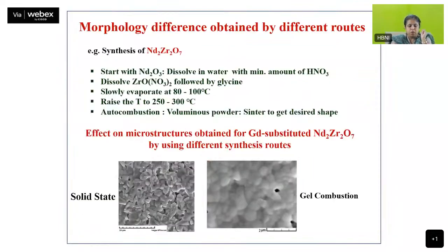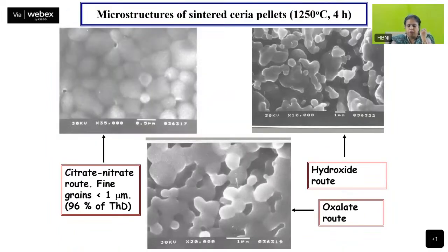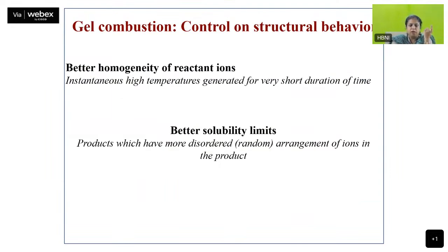Now, just a comparison. This is the Nd2Zr2O7 synthesized by solid state, and this is by gel combustion. You get nice, very defined grains. This is cerium oxide obtained by making hydroxide and heating, by oxalate, and by gel combustion. So the morphology that you're observing is a clear indication of the difference in the product that you can get.